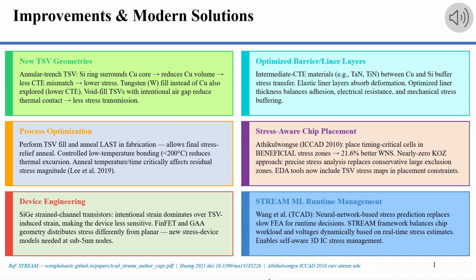The second one is using tungsten as an alternative material. We are looking at tungsten because its coefficient of thermal expansion is much closer to silicon compared to copper. Using tungsten reduces the mismatch right from the material level. The third one is optimized barrier layers. We use thin layers like titanium nitride between the copper and silicon. These act as a material cushion or buffer, absorbing some of the stress before it reaches the transistors.